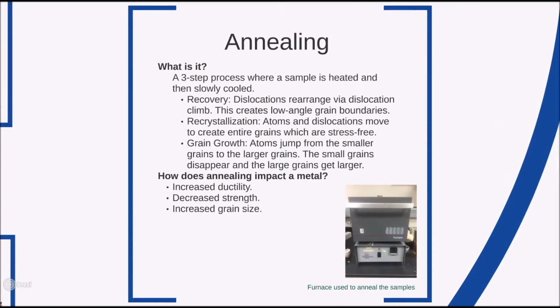During the recovery phase, dislocations within the material rearrange through a method known as dislocation climb. While this is taking place, the grains are moving to a lower energy orientation with low angle grain boundaries. Once these low angle boundaries are formed, recrystallization begins. Atoms and dislocations continue to move. As they move, they create entire grains which are stress-free and without dislocations. These new grains have low internal energy, so it is favorable for them to be formed.